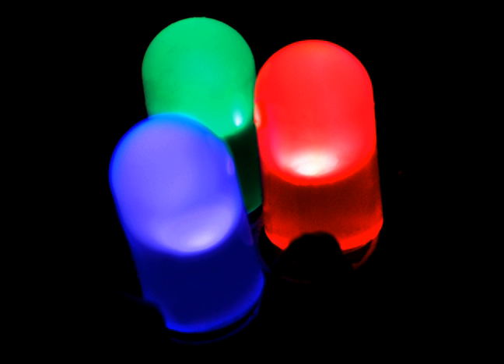High power. High-power LEDs (HP-LEDs) or high-output LEDs (HO-LEDs) can be driven at currents from hundreds of mA to more than an ampere, compared with the tens of mA for other LEDs. Some can emit over 1,000 lumens. LED power densities up to 300 W per square centimeter have been achieved. Since overheating is destructive, the HP-LEDs must be mounted on a heat sink to allow for heat dissipation. If the heat from an HP LED is not removed, the device fails in seconds.